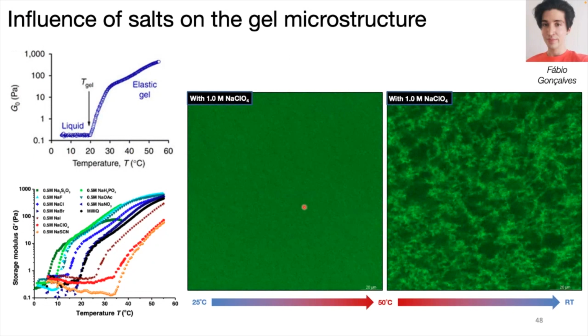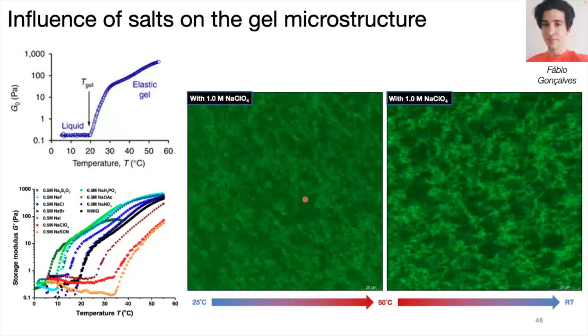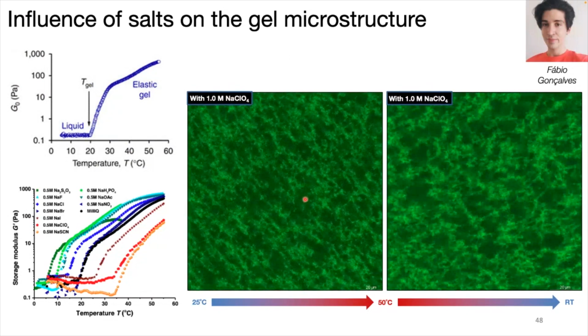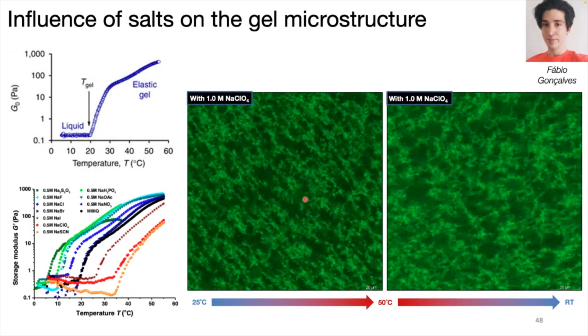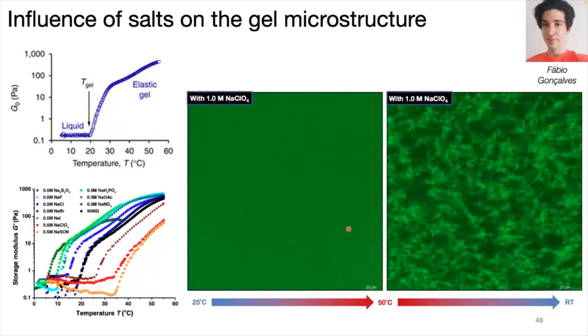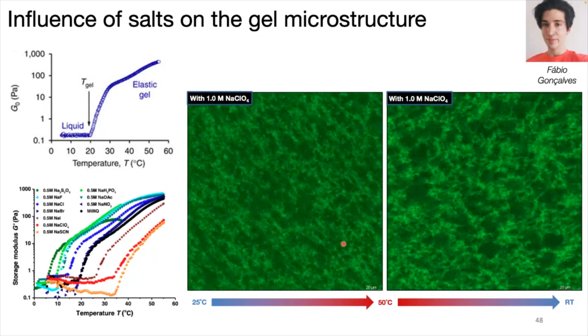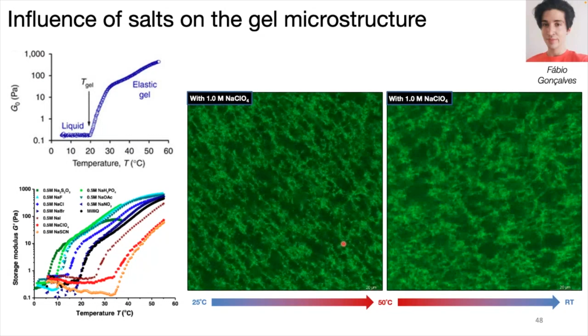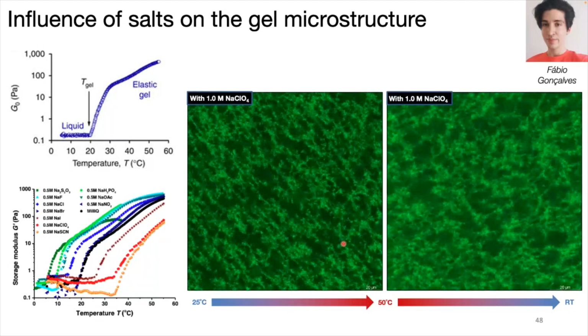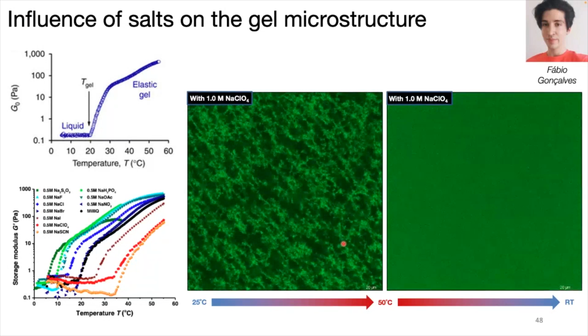So here we can follow how the gel forms, and actually it looks almost like an instantaneous process, right? So there is nothing there, and then everything is formed. I'll just play it again. So you have a very uniform solution of PIC polymers, and then once it reaches a certain temperature, the whole hydrogel just forms in one go. And then the opposite, if you cool down, the hydrogel also disappears completely.